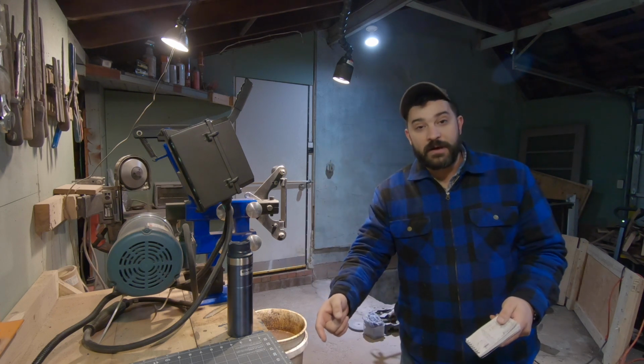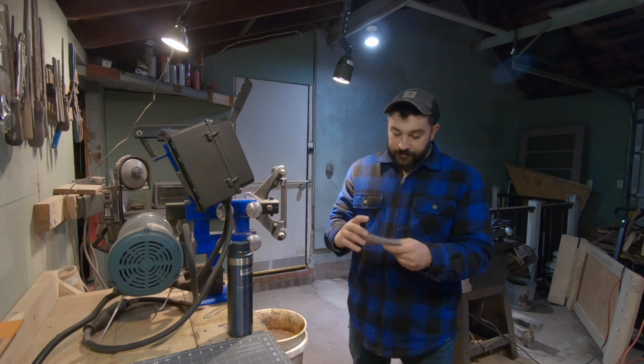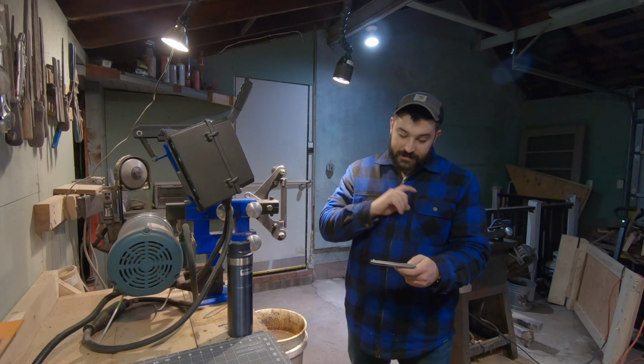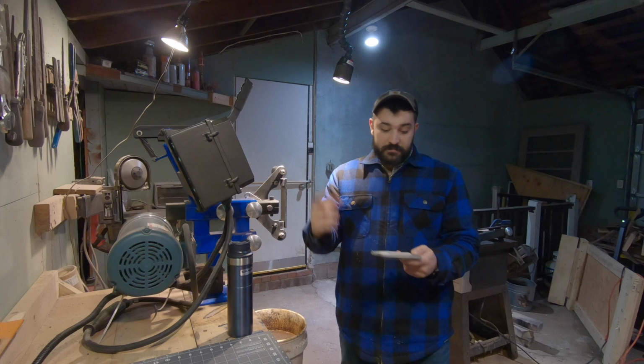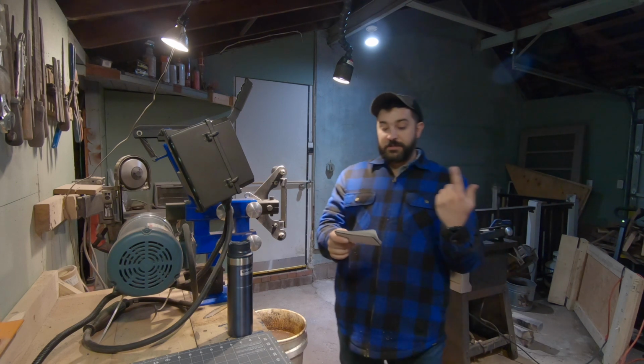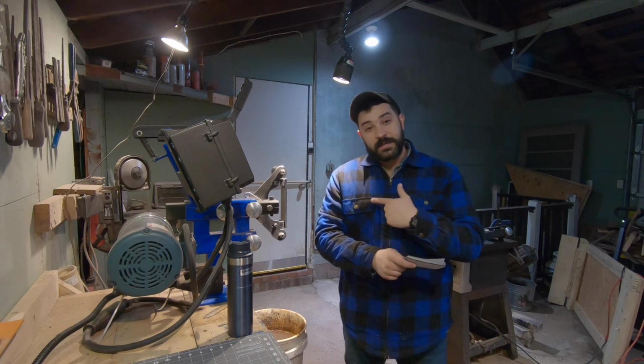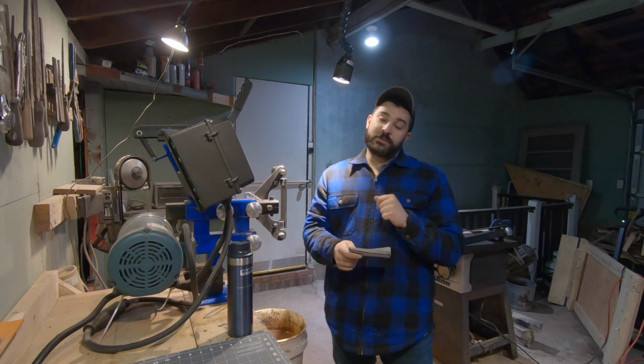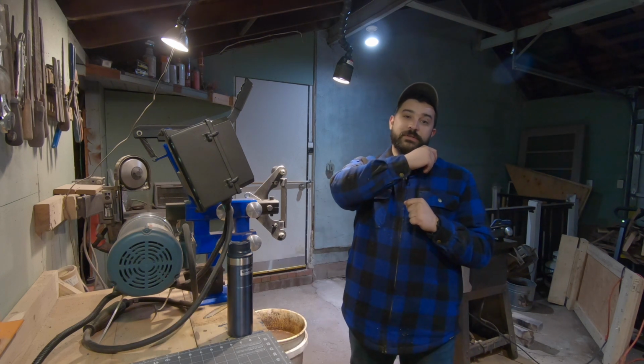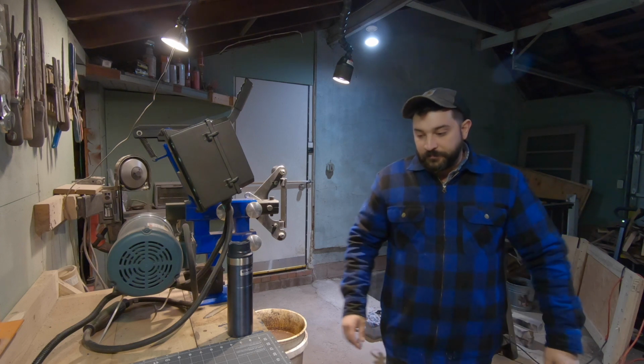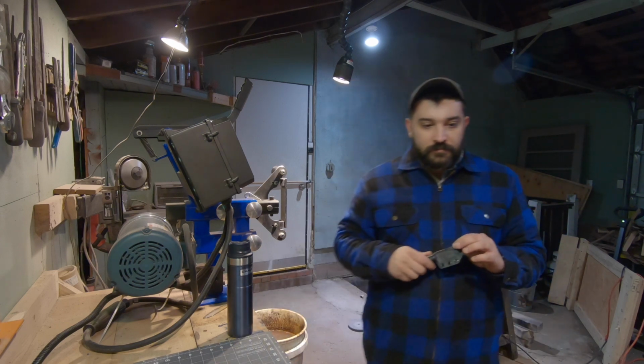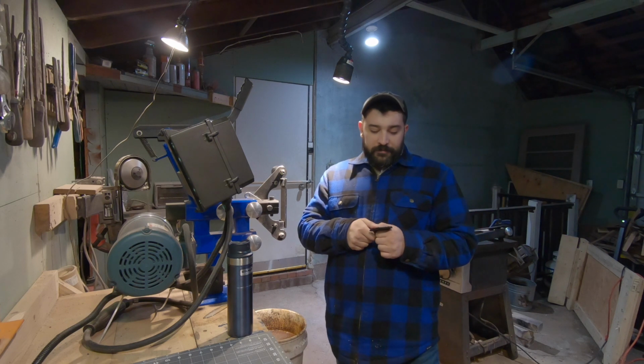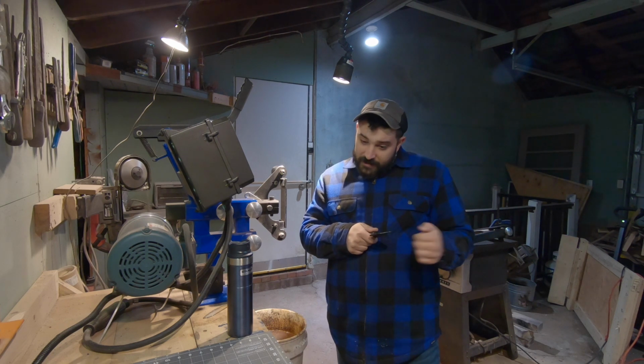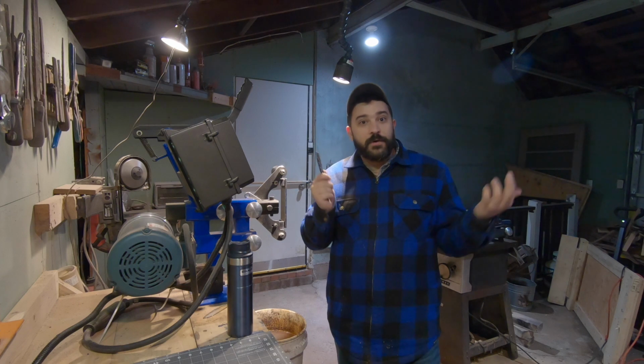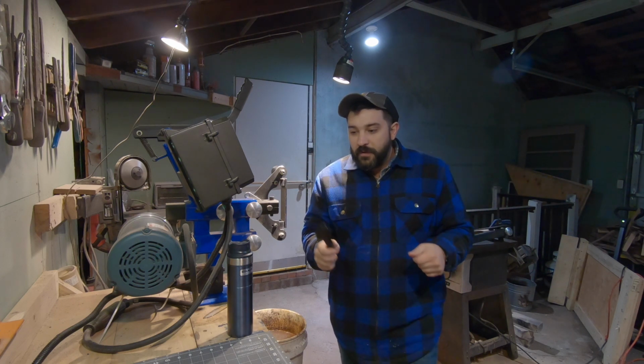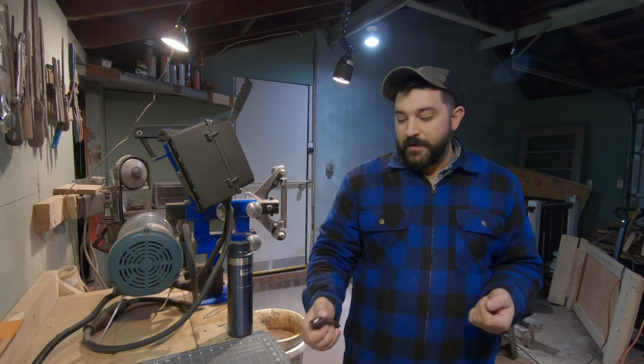So this one, initial 70 passes times 2, 140 cuts. Regrind, 15 thou behind the edge. We got 100 passes or 200 cuts. That's a 42.8% increase, and a difference of 35.2. That's not bad. It's not bad for a 3V. I would take that all day. If it had a different heat treat and if it was a little bit thinner, it probably would have done better. Those are factors that correlate with those types of numbers.